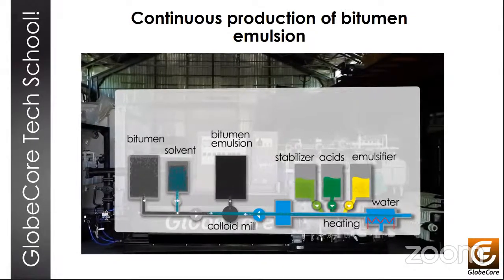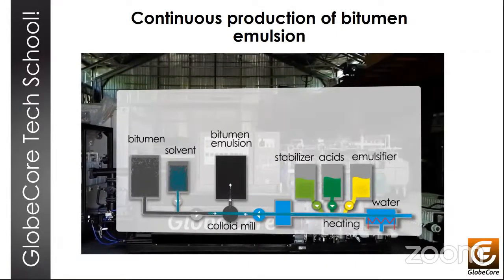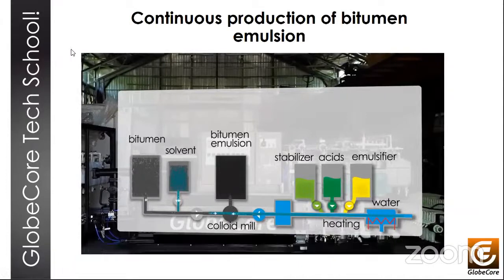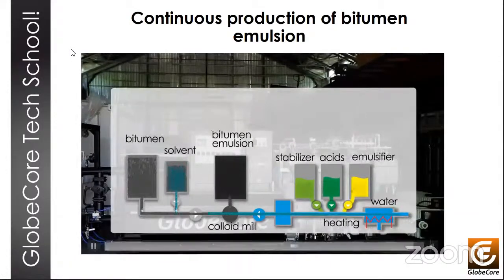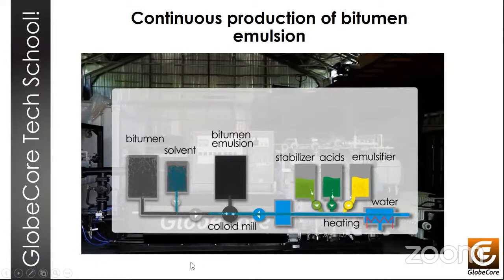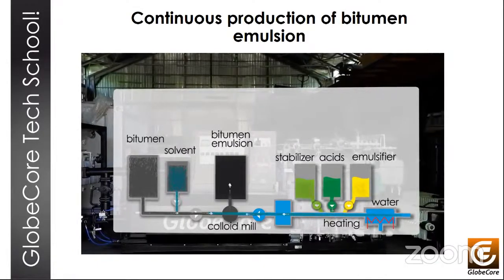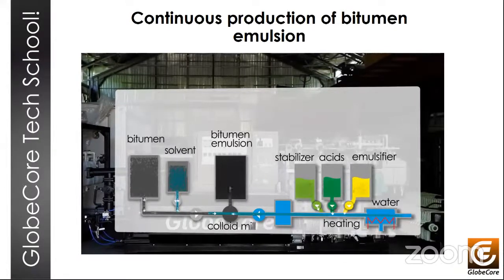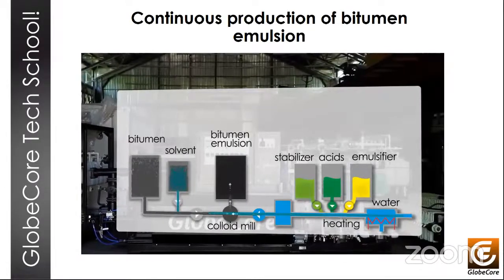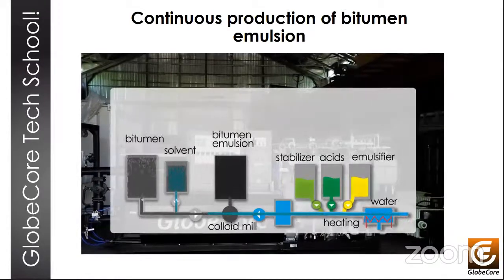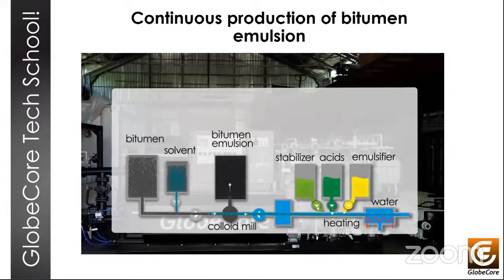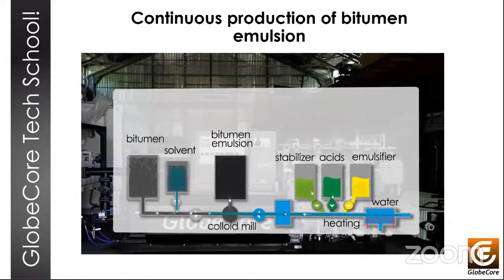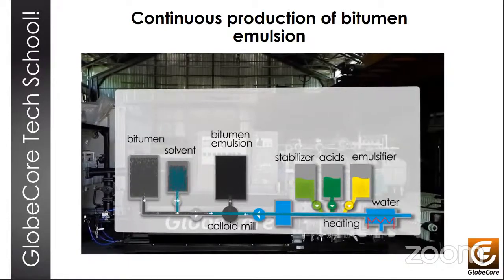When making an emulsion, it's possible to use various polymer modifiers such as latexes, SBS, or other additives to bitumen. In this case, it becomes necessary to equip the plant with additional assemblies, as well as to implement appropriate technical solutions. Latex, for example, is sensitive to external factors that can cause it to break down, clogging pumps or pipelines. In the case of SBS polymers, it's usually necessary to output the emulsion at a temperature above the boiling point of water, which requires overpressure, and then cooling of the product before it's fed into the storage tank with a transition to normal atmospheric pressure.